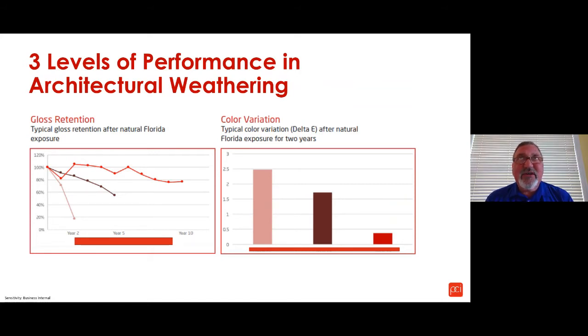Now, if you think of a project or an in-use service of a product that is not going to be in South Florida, say if you're north of the Mason-Dixon line, then those products see significantly less UV exposure. And so would you need a super durable product if you are not getting the intense UV exposure that you get down in Florida? Now, if you've got products being shipped all over the country, you pretty much have to go that route because you are going to be exposed to it at least at some point in time. On the other side is the color variation, and that's typically measured in what's called delta E, and all that really is a measurement of one color position to another color position over time. And so we're exposed to the outdoors. You can see the one, and after 2 years shifts about 2.5 color units.